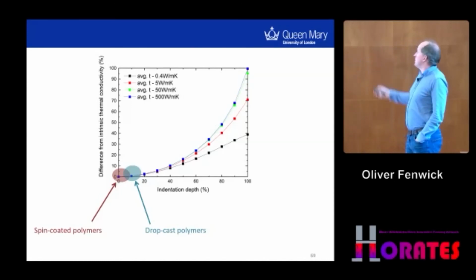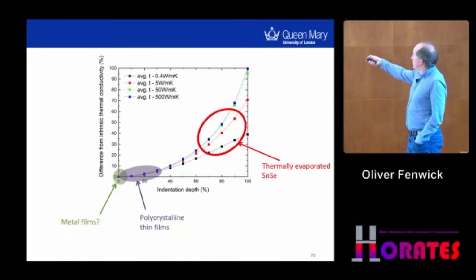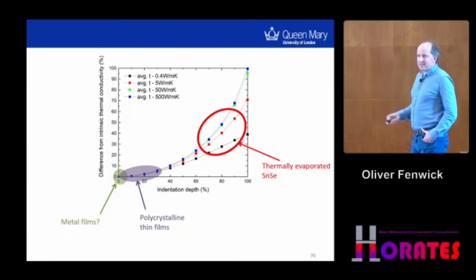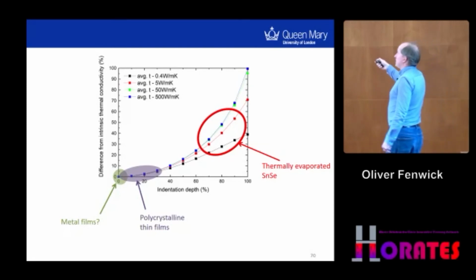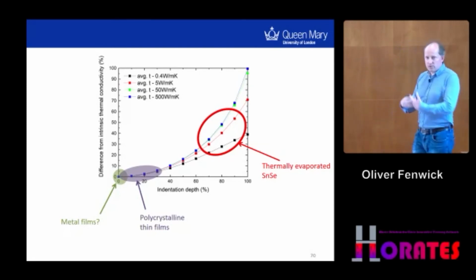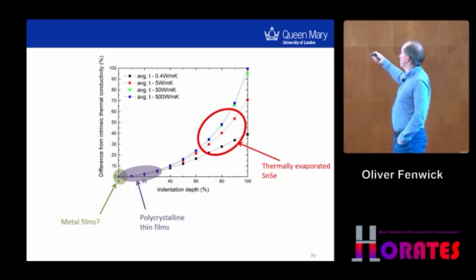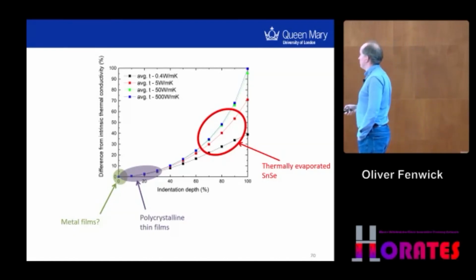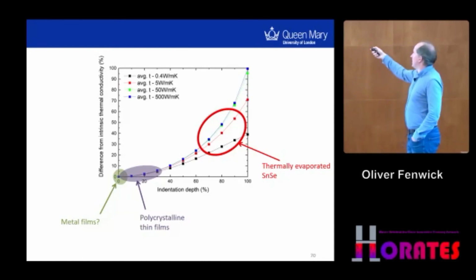Drop cast polymers, maybe a bit more. Metal films, if we evaporate some of them, we tested some of them, yes, it should be in that range again. Polycrystalline films, it depends on the material, right? We saw a bad case with the methylammonium lead iodide, but probably most are in this kind of region. The thermally evaporated tin selenides is probably somewhere here. I haven't modeled exactly the same morphology, so I can't be precise, but it seems the indentations were definitely well over half of the thickness of the film. So that is why that one failed.